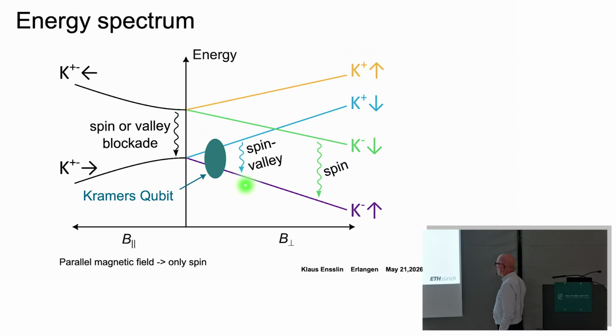Now what happens if you apply a perpendicular magnetic field? A perpendicular magnetic field couples to the spin, but it also couples to the orbital motion of the electrons. And the K's and the K primes, they're orbital quantum numbers. And actually what happens is, because of the Berry curvature in K space that's related to these topological properties, the orbital magnetic moment that you find for these electrons leads to a linear shift in magnetic field. So we call this the orbital or the valley-Zeeman effect. And the valley-Zeeman g factor can be anything between 20 and 200, depending on the gate voltages that you apply.